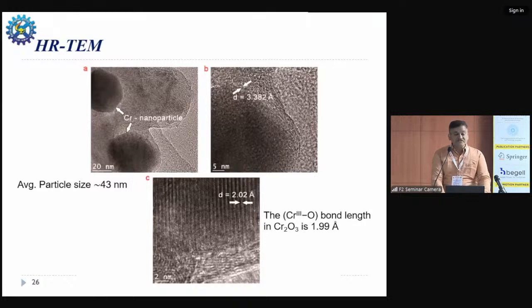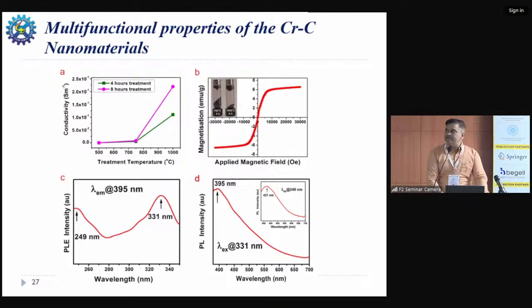And this is the typical structure formed, where you have chromium nanoparticles around 40 nanometer surrounded by carbon layers, and the interlayer spacing is also shown here. And here again, we got very good electrical conductivity for the materials, and the magnetic property is fairly higher, almost 6 EMU per gram, primarily because it is not just impurities, even the chromium contributes to certain magnetism, and therefore compared to the previous material, here we got fairly higher magnetic behavior.